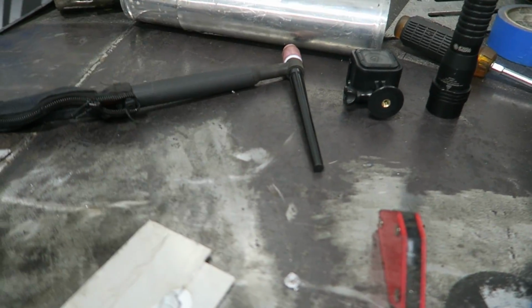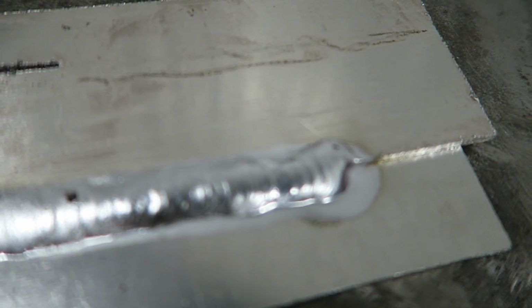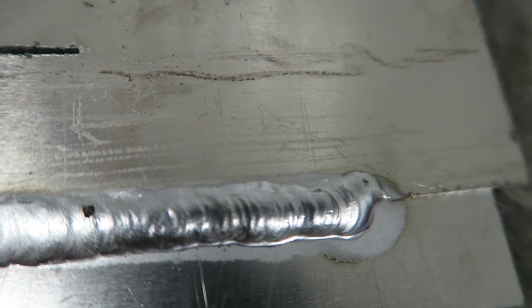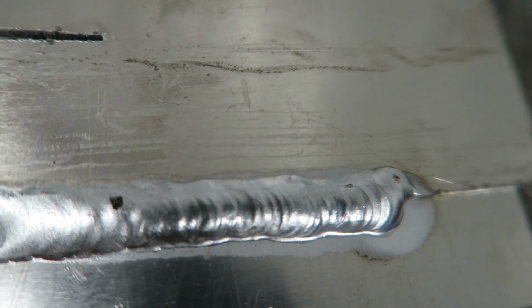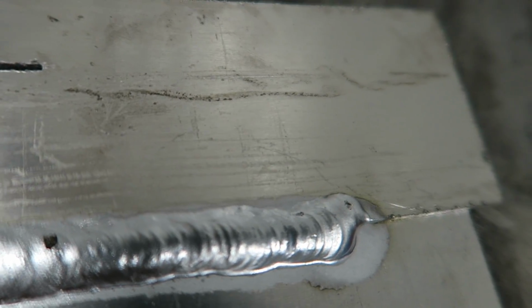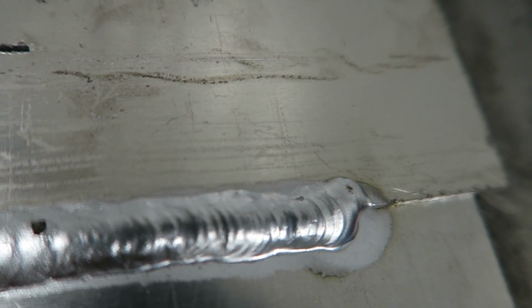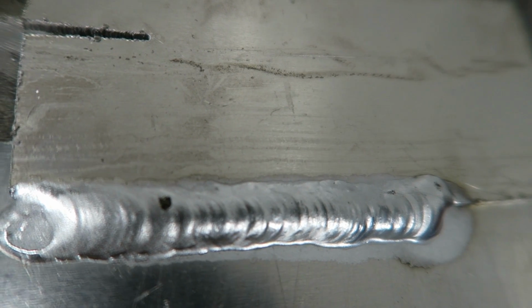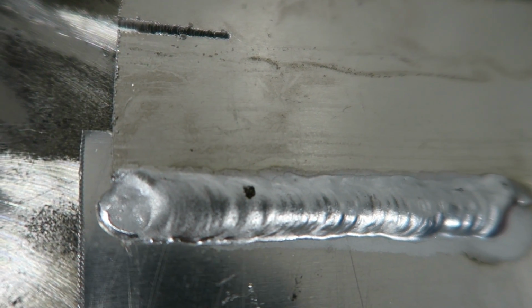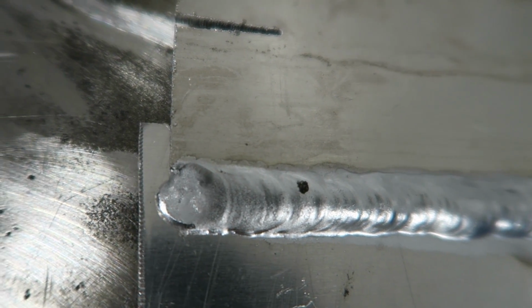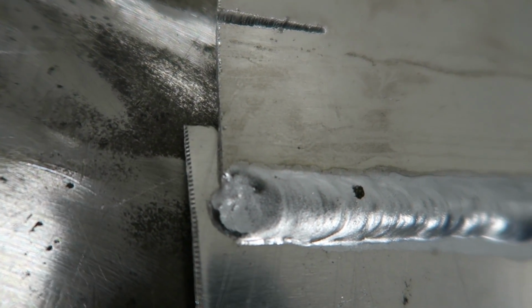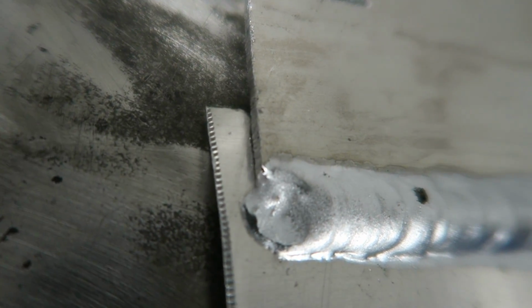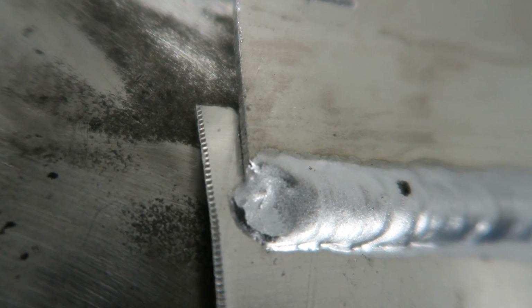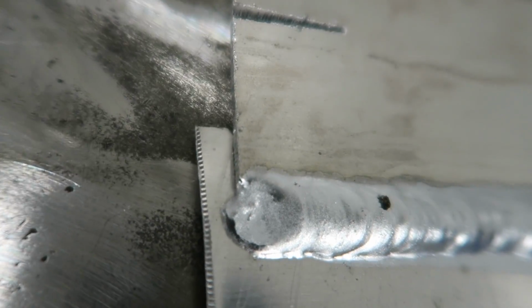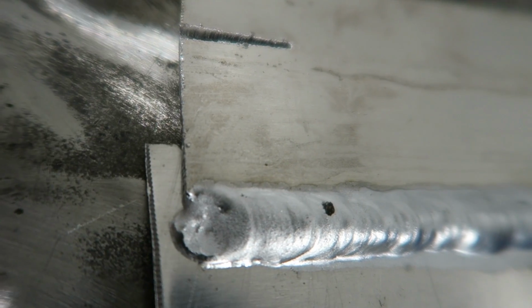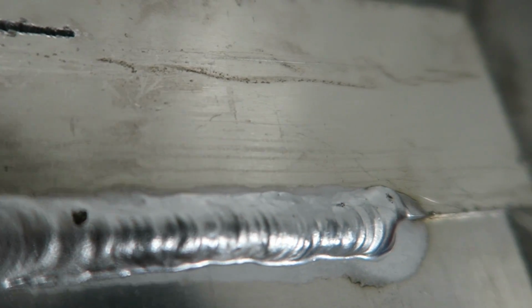Alright, so here we go. This is the first piece we did. Now you'll see that this bead is super, super fat. This one was welded with too much heat in the beginning, therefore it's very, very wide, very fat. And then as we move down the bead, you can see it change significantly. You see where you're losing that dime effect, and it's just starting to look like a pond of melted metal. That was me keeping a consistent 120 amps all the way to the end. And if you can see right there, there's a huge crater at the end of this weld, which is something you don't want. And you also see that the puddle started to fan out a little bit. That is also something you do not want, the puddle fanning out from where you started.